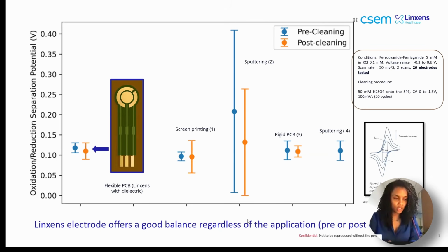For healthcare application, in general, we have gold as finishing, or silver sometimes, platinum sometimes too, but nickel not, because nickel can passivate easily, and the passivation of the nickel can induce a less good conductivity. So in general, we don't have a request from our customer to use nickel as a final layer. It's just an intermediate layer to isolate the copper to the system.